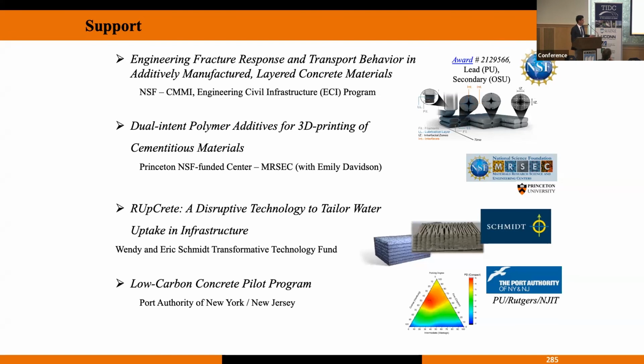We do have a small project with Port Authority of New York, New Jersey, where we are looking into particle packing. Particle packing is another example of things that has been done, but maybe it's time to look into it in more detail. ACI has a few committees on aggregate packing and particle size optimization. Just by changing your particle size distribution, introducing intermediate aggregates, you can improve particle packing by quite a bit and help reduce the cement content by about 20%. We did this for Wisconsin DOT in 2015, 2016, and there was a lot of saving just using ordinary Portland cement concrete.